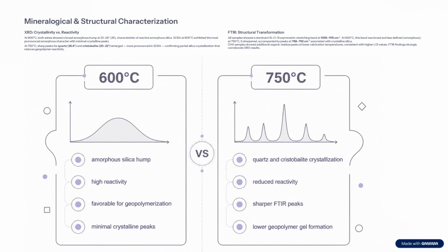For the XRD, crystallinity at 600 centigrade: both ashes show a broad amorphous hump at 22 to 24 degrees 2 theta, characteristic of reactive amorphous silica. SCBA at 600 centigrade exhibits the most pronounced amorphous character with minimum crystalline peaks. At 750 centigrade, sharp peaks appear for quartz at 26.6 degrees and around 20 to 22 degrees for cristobalite, more pronounced in CHA, confirming partial silica crystallization that reduces geopolymer activity.